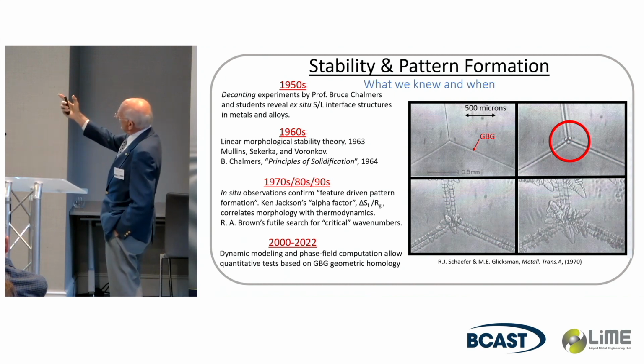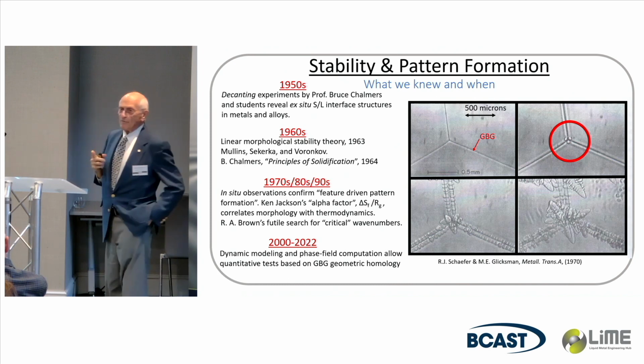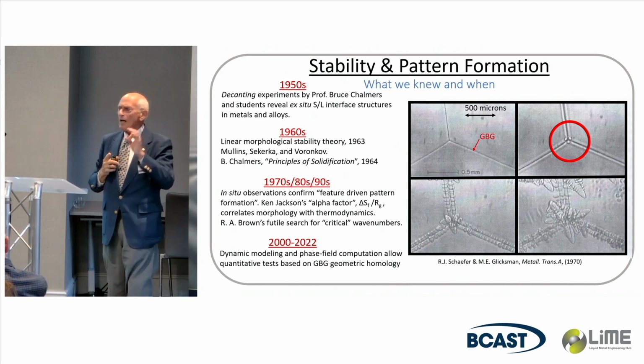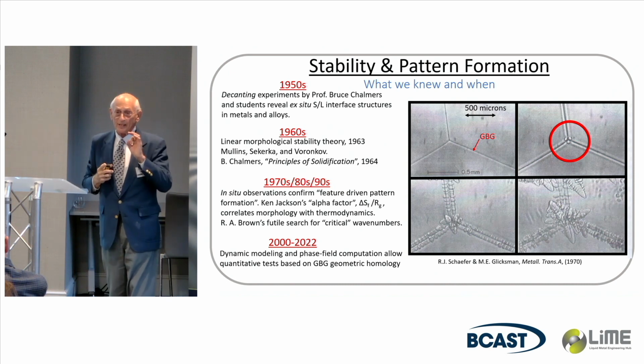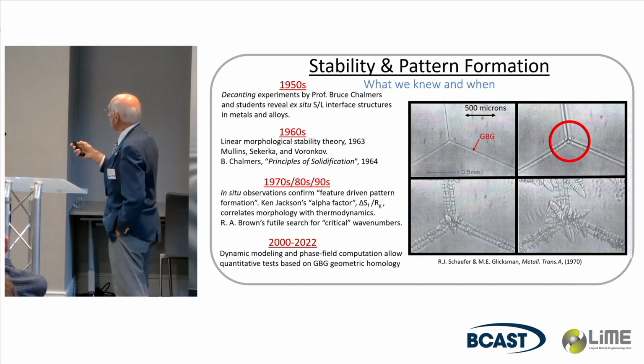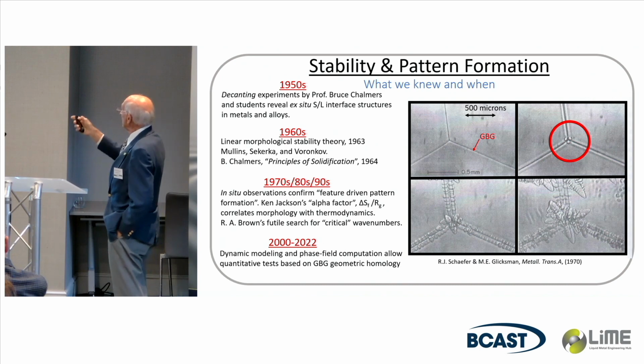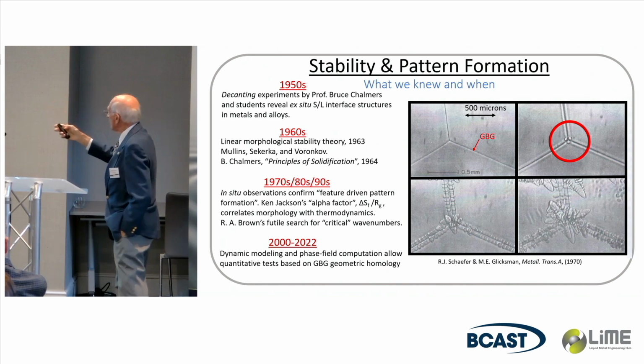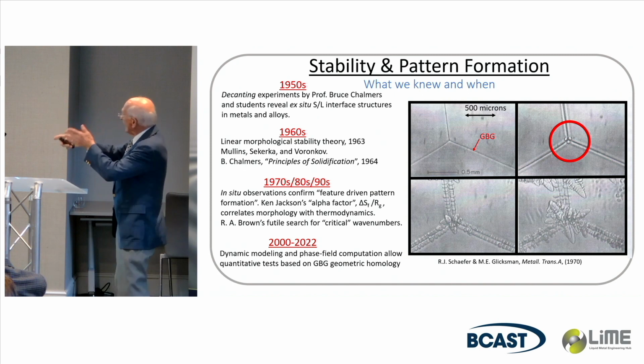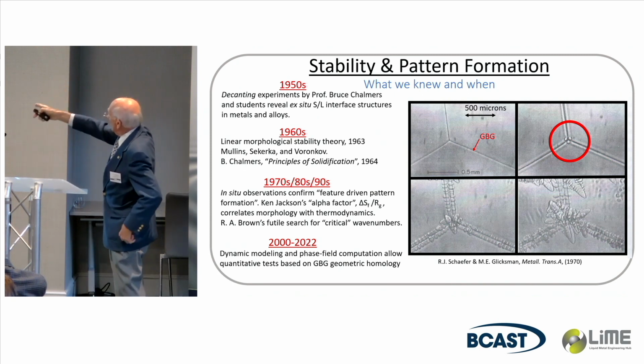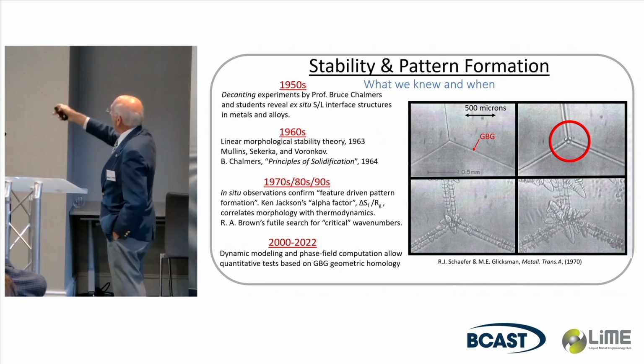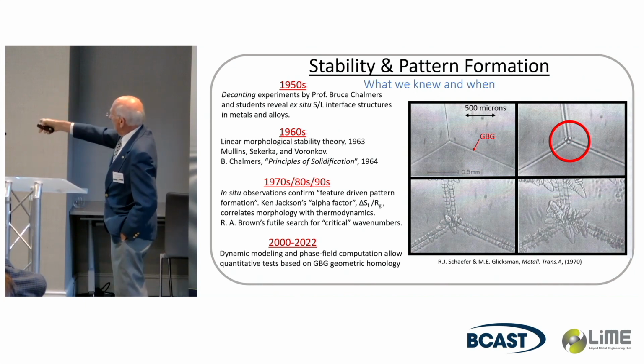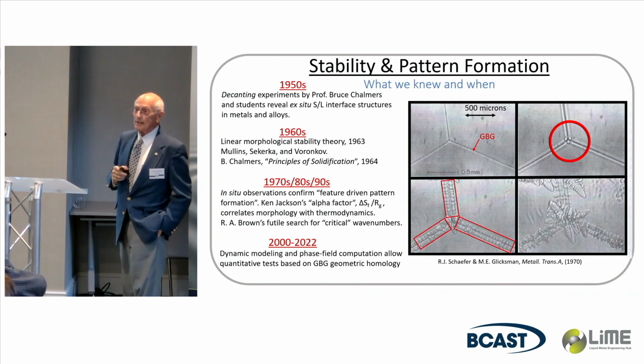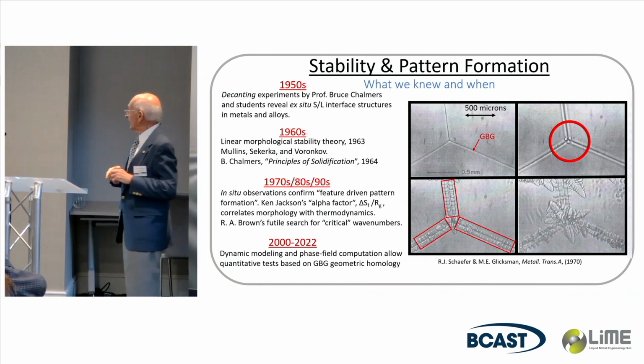And as the solidification front advances toward you, I circled the fact that you suddenly see 3 so-called pre-dendritic discs. And those discs actually lead to the breakdown of the furrow that builds up out of these linear grain boundary grooves. And what happens is it kicks off an instability in the other direction, and you can see them developing as adjacent helix.